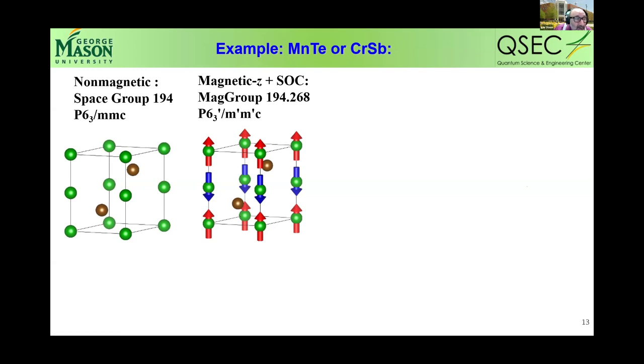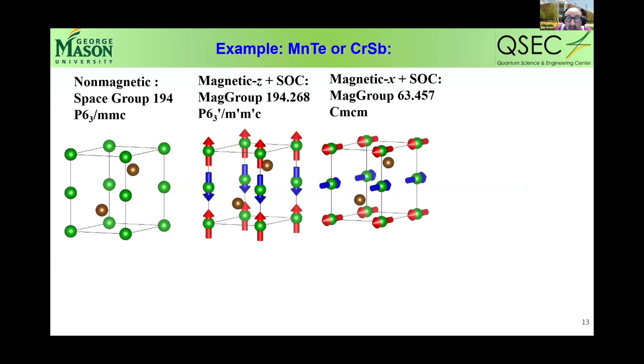So let's look at the non-magnetic space group. It is a group called 194. It has six-fold symmetry. This is the standard crystallographic notation for this group. Now we introduce magnetism in the Shubnikov sense, so we include spin-orbit coupling. Then if my magnetic moments are along 0, 0, 1, then the six-fold symmetry remains. There is a particular magnetic group.